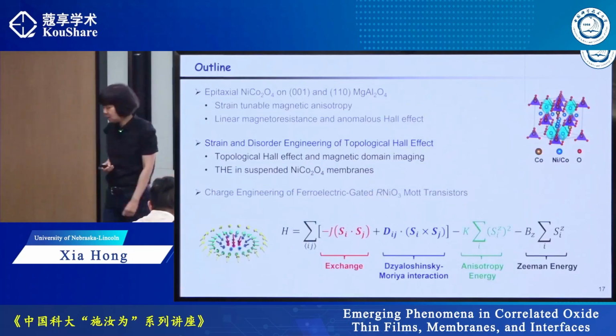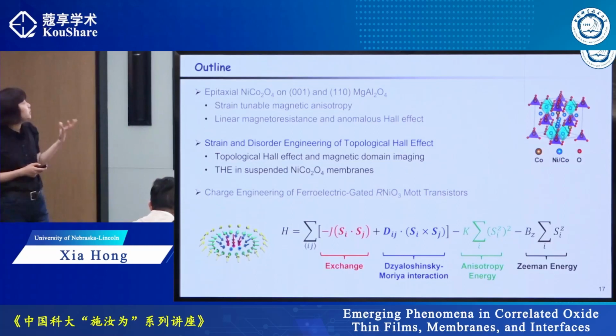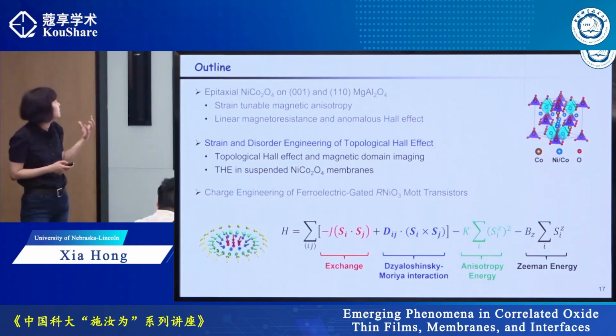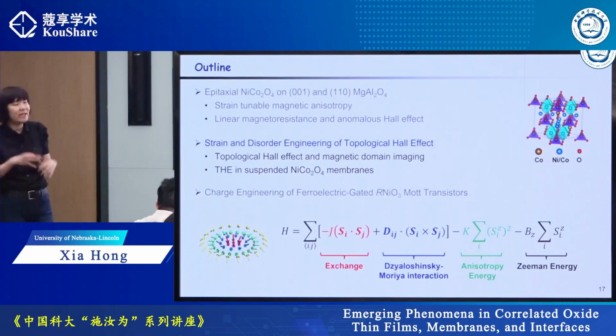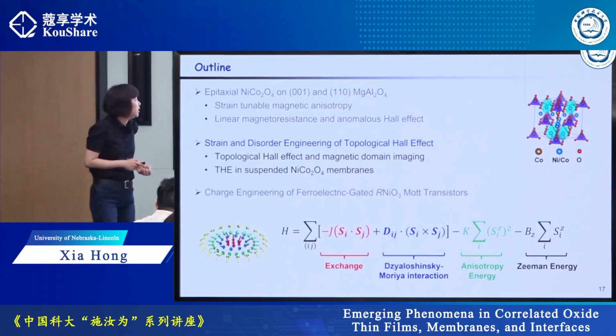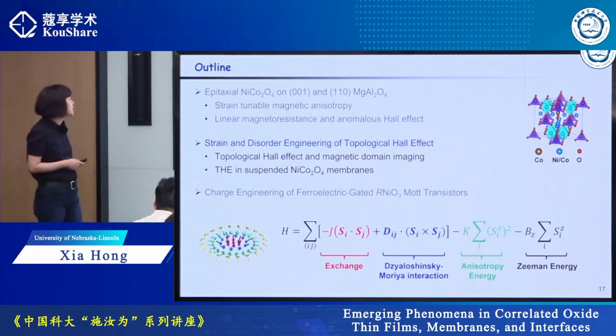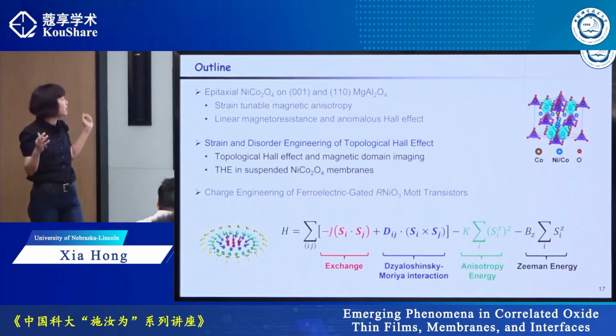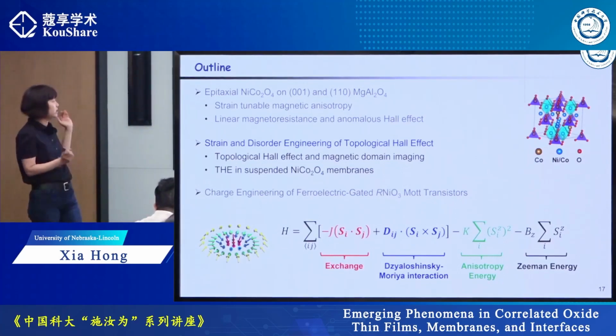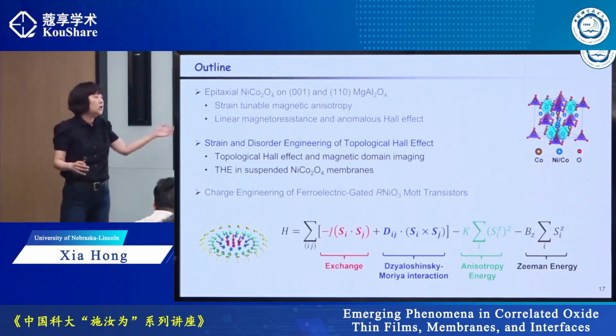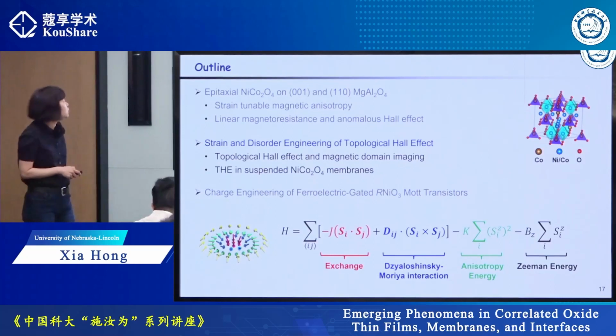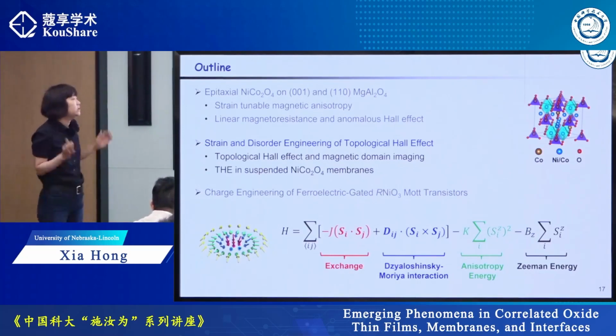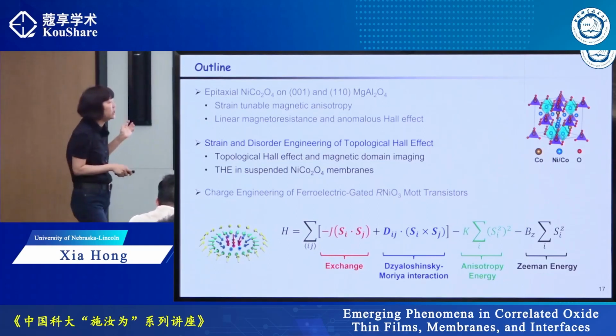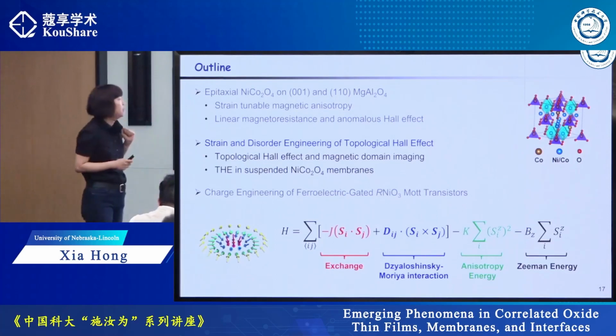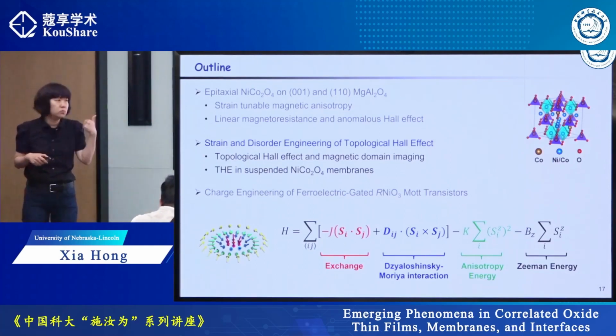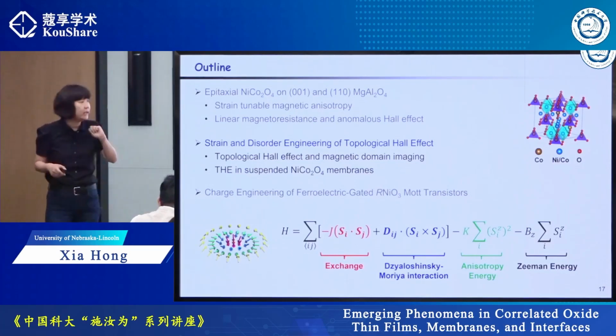Okay, and another thing we observe is something on top of anomalous Hall that is normally associated with a chiral spin texture. So we know that most of the well-studied skyrmions, right? You have a background with spin in one direction, and at the core, you have the other direction, and spins try to rotate either in the Néel type or Bloch type. And the key to have a non-collinear spin alignment when you change the spin direction is what's known as the Dzyaloshinskii-Moriya interaction. So this one requires you either break the inversion symmetry and have high spin-orbit coupling.